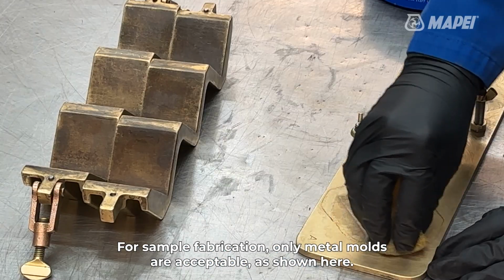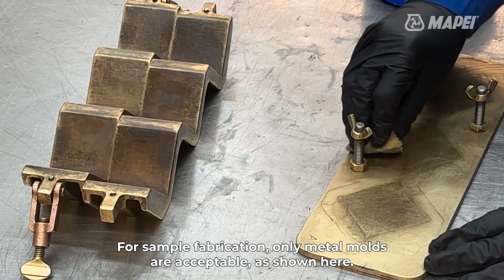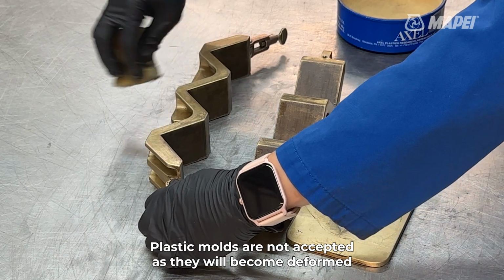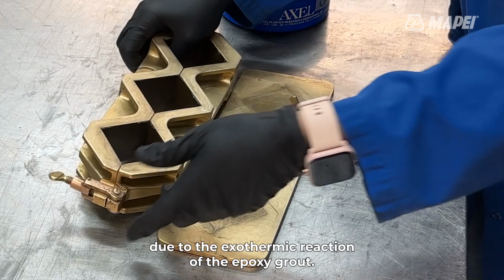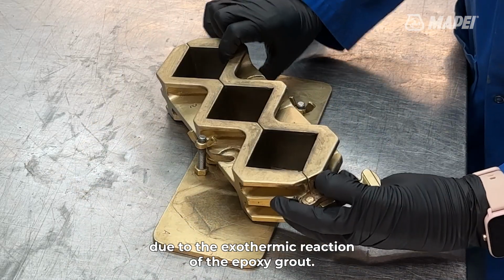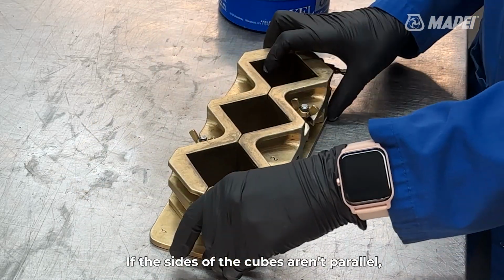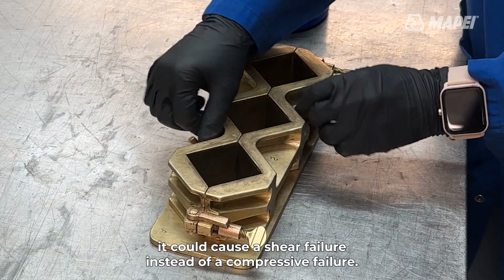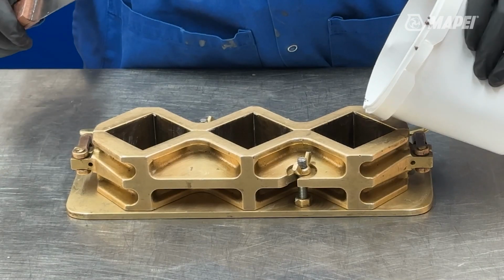For sample fabrication, only metal molds are acceptable as shown here. Plastic molds are not accepted as they will become deformed due to the exothermic reaction of the epoxy grout. If the sides of the cubes aren't parallel, it could cause a shear failure instead of a compressive failure.